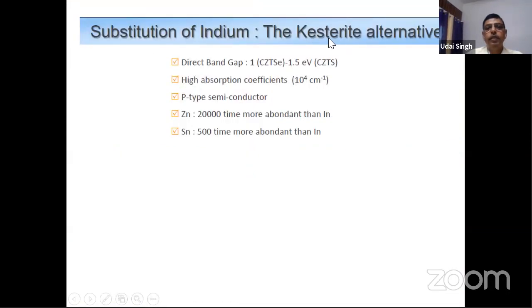Now this CZTS, kesterite, if you are trying to replace indium. Again it's a direct band gap material, copper zinc tin selenide or copper zinc tin sulfide. You can vary the band gap from 1 to 1.5 electron volt. This also has a high absorption coefficient. It's again a p-type semiconductor. Zinc is abundant, tin is also abundant on earth, so they are earth abundant materials.